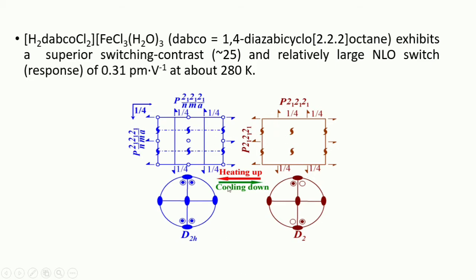This is the case. We can say this is a molecule, H2 dabco, FeCl3, H2O thrice. Dabco means 1,4-diazabicyclo[2.2.2]octane. It actually exhibits a superior switching contrast of up to 25 and a relatively large non-linear optical switch of 0.31 at about 280 Kelvin. This is a non-linear optical molecule which shows non-linear optical properties at low temperature, where the symmetry operations are quite low.